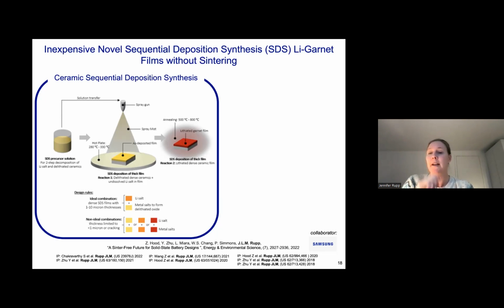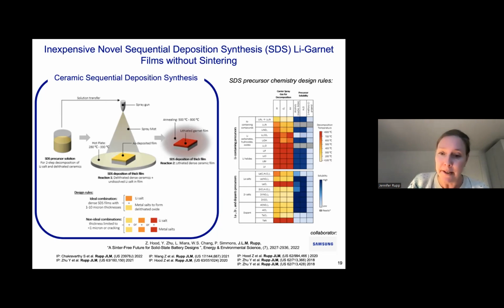The lithium diffuses into the structure, and then you have a second transformation in how the phases are forming. Why this is smart is that you have to control the drying when you go from a direct wet to a direct solid-state reaction, and you don't start from powders. So we avoid the need to have powders shipped to our lab or any entity, and just come directly from the precursors and transform them directly into the right metal oxides. This is a quite cool method because it allows you to go much more easily to area upscaling. It's very cheap and it doesn't need any fancy vacuum.